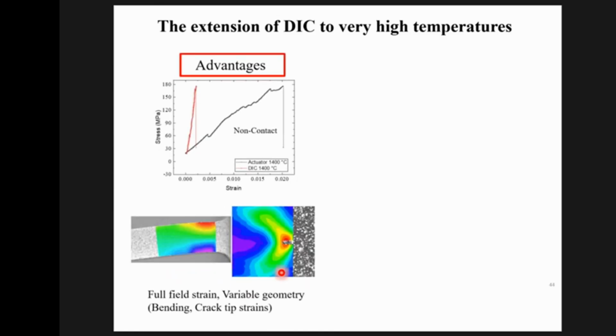The advantages are obvious. This is what the machine crosshead gives you, and this is what the DIC gives you about the stress strain behavior. So there are all kinds of displacements happening in your machine which have to be subtracted out. And extensometry runs into other problems. An extensometer breaks every 3 runs and it gets expensive. So there are a lot of advantages of DIC. You get full strain field measurements, and this is the strain contour at a crack tip. So one can do all kinds of things with non-standard geometries.